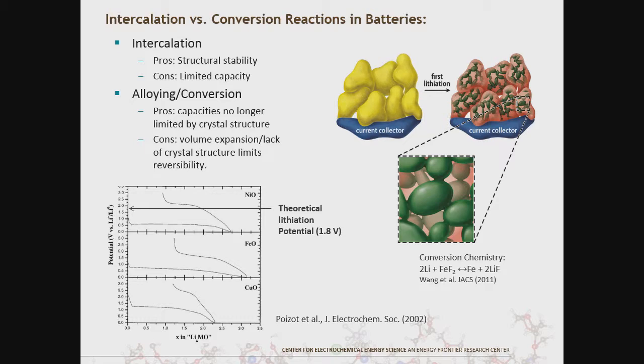You can see this shows, I think, one of the key characteristics of conversion reactions. This is nickel oxide. You can see when you lithiate it, the observed potential for lithiation is typically around 0.6 volts, but theoretically it should be up around 1.7 or 1.8 volts. So this is a very substantial overpotential, which we'd like to see if we can control.